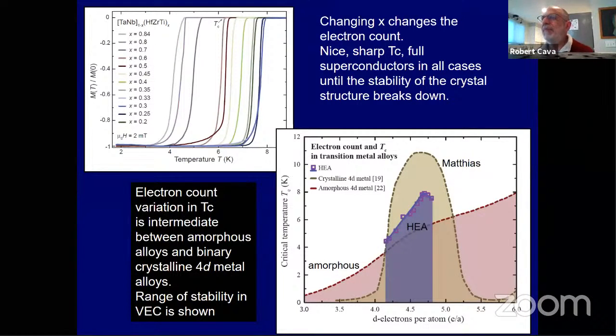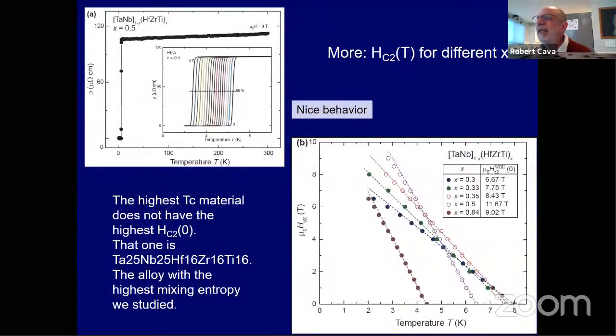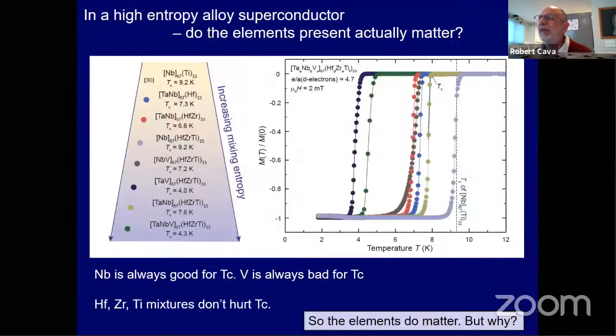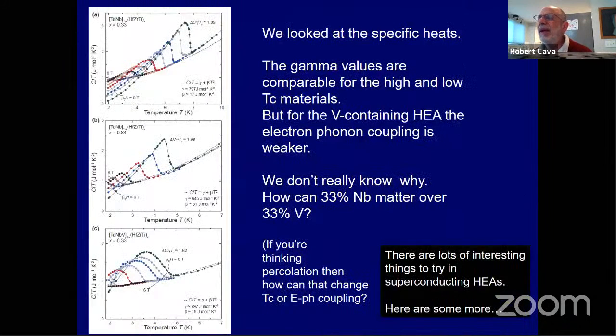Then you can plot the electron count variation of TC by changing the ratio of the constituents, and you discover that your high entropy alloy superconducting transition, depending on the electron count, is somewhere in between what you get for a real amorphous solid and a crystalline solid. And then you can look at the upper critical field as a function of temperature, and as a function of composition of the alloy. Well, let's not worry about this because I don't have too much time.